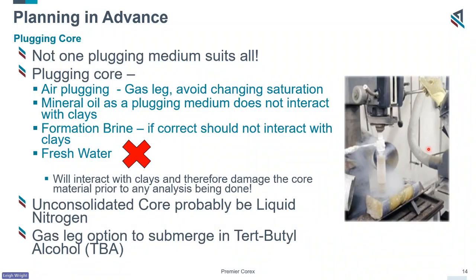One of the things that we do a lot, and I was talking about that with the unconsolidated core that I had to drive to a CAT scanner, that was frozen. So the in situ fluids in that core were used to maintain the structure and the integrity of the 3-foot sections. We then freeze the different sections in liquid nitrogen and then plug using liquid nitrogen as a medium. Now, we know from, again, in-house with our cryogenic SEM facility, that when you flash freeze the samples, the clays and the internal fabric of the rock are not damaged if done correctly.